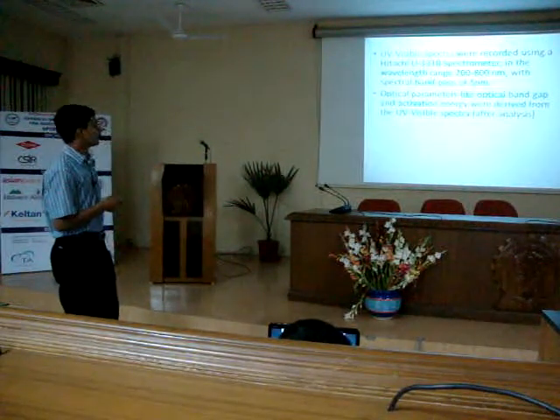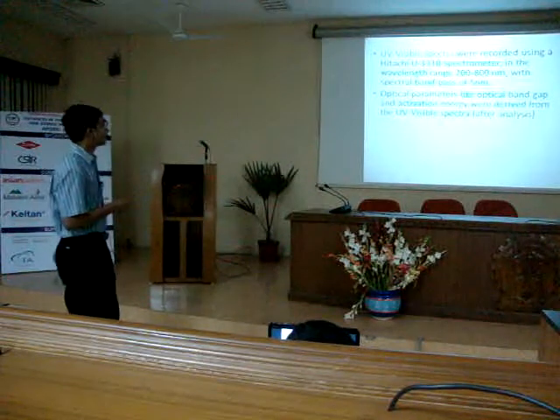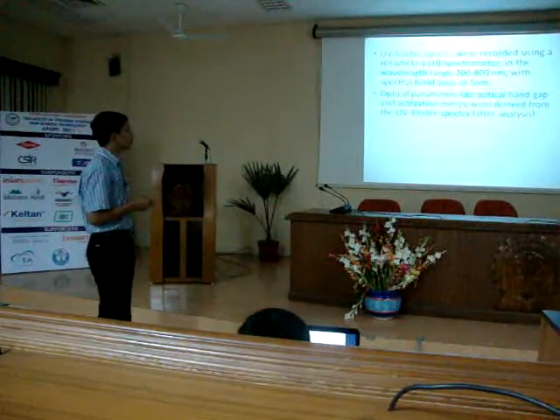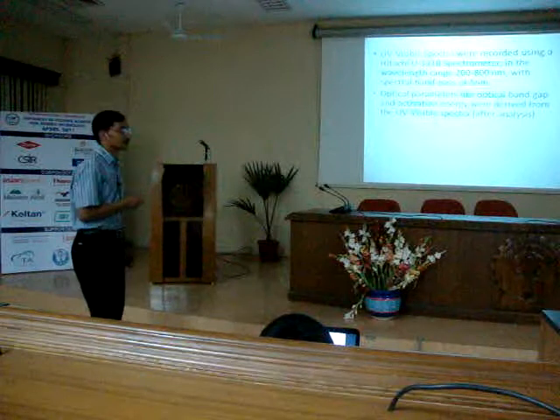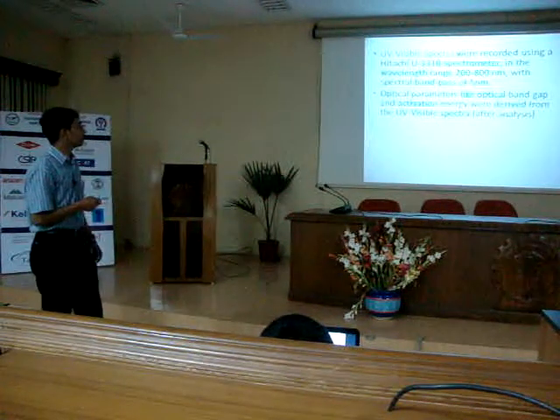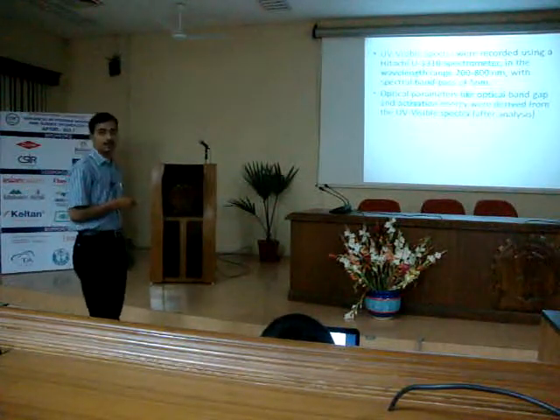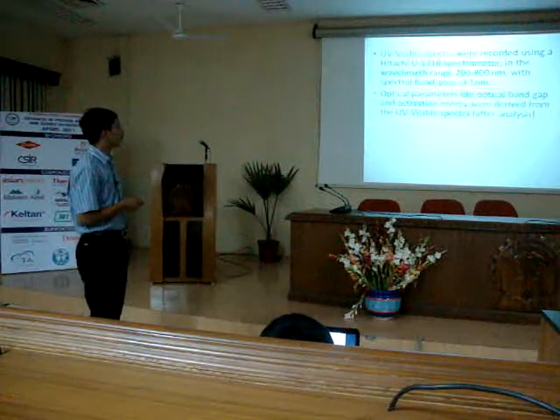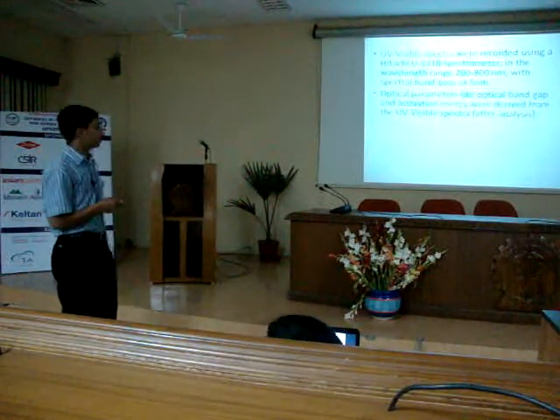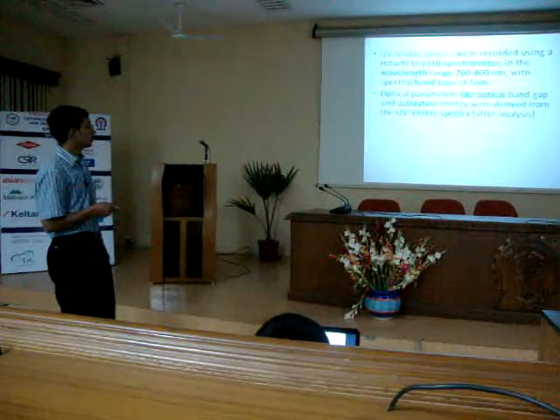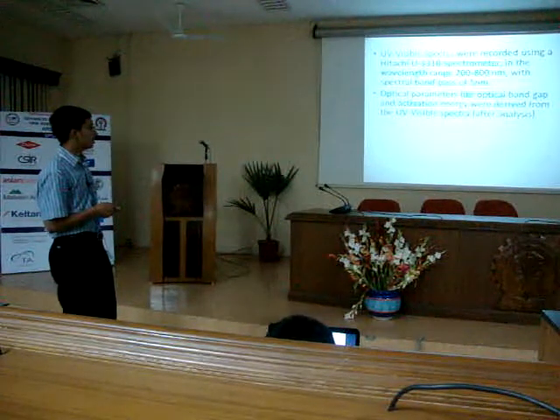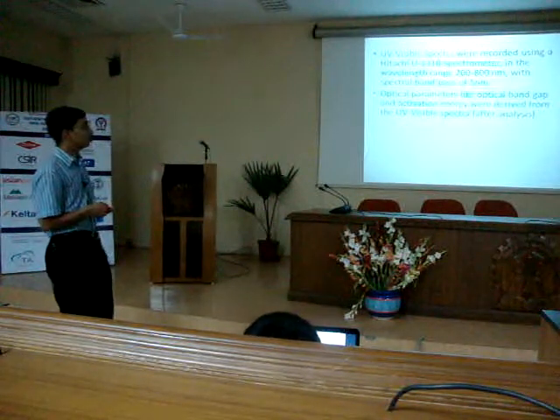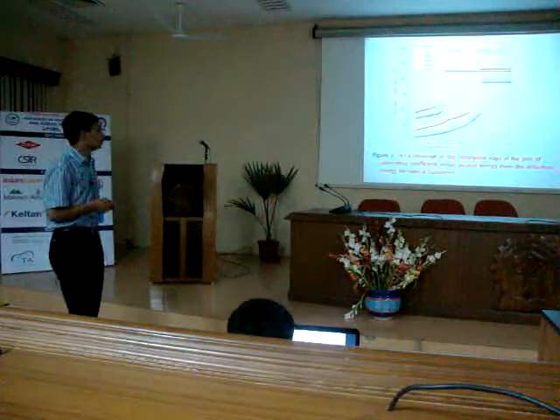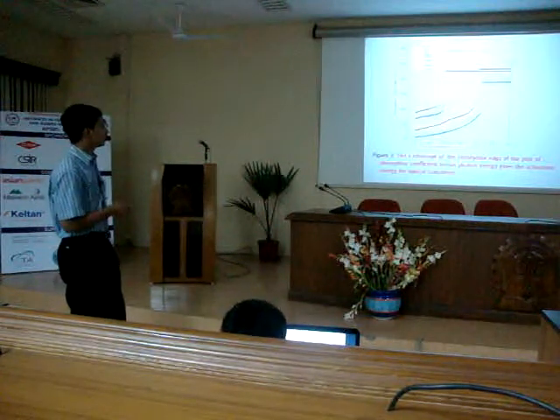Now this is about the UV visible spectra. UV visible spectra were recorded using a Hitachi U3310 spectrometer in the wavelength range of 200 to 800 nanometers with a spectral band pass of 5 nanometers. Optical parameters like optical band gap and activation energy were derived from the UV visible spectra. So this is the graph for the UV visible.